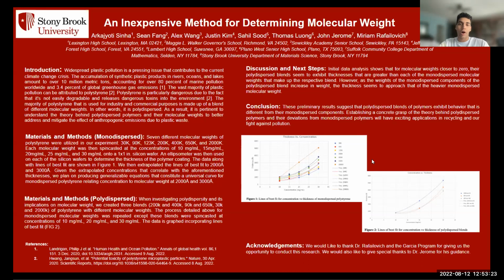We first studied monodispersed polystyrene using the molecular weights 30K, 90K, 123K, 200K, 400K, 650K, and 2000K. These molecular weights were spin casted at the concentrations 10 milligrams per milliliter, 15 milligrams per milliliter, 20 milligrams per milliliter, 25 milligrams per milliliter, and 30 milligrams per milliliter. We then used the ellipsometer to measure the thickness of the polymer coating on each silicon wafer. The results are graphed along with their lines of best fit in figure 1.